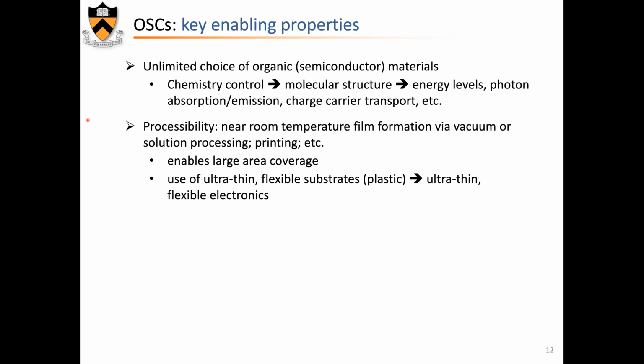The other one is processability. All these molecules are deposited either via vacuum evaporation or from solution, especially for polymers, essentially near room temperature. And room temperature allows you, and that is extremely important, the use of ultra-thin, flexible plastic substrate. And that, of course, is what leads to flexible electronics that is so important these days. So ultra-thin, because of the room temperature processability, you can use very flexible substrate.